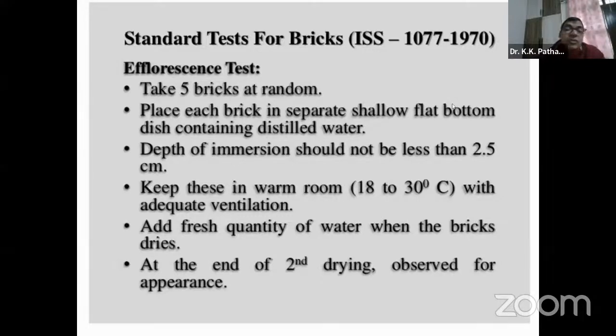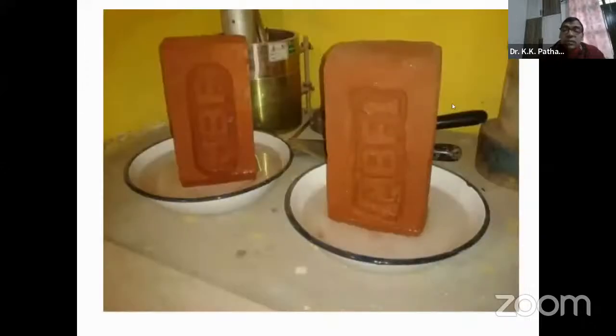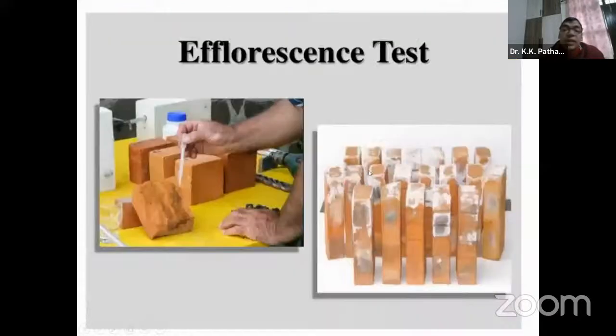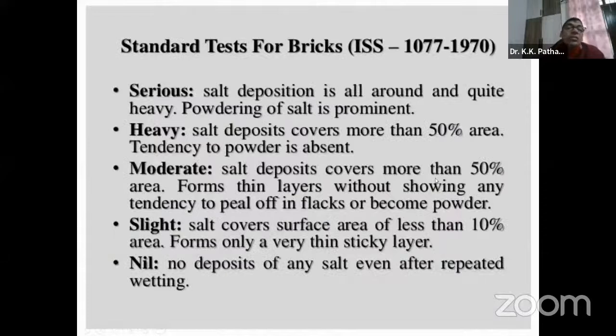I think those who have studied building materials, this was there. So this is the test we do in the lab for efflorescence, and then we check after 24 hours, after drying, if there are white patches, it means there is efflorescence. Efflorescence is measured as serious, heavy, moderate, slight, and nil. If it is slight or nil, we can go with construction. But for those old buildings which have already been made, now we have to do the treatment. There are some acid treatments to remove efflorescence if the bricks are already used. Those are costly affairs, but now there are ways by which we can rectify it.